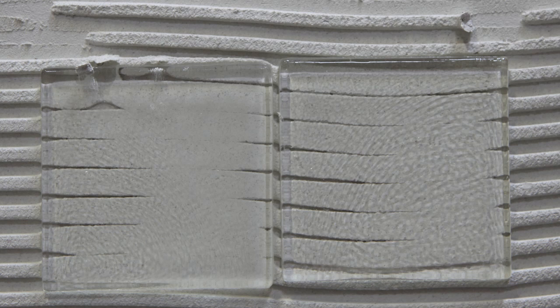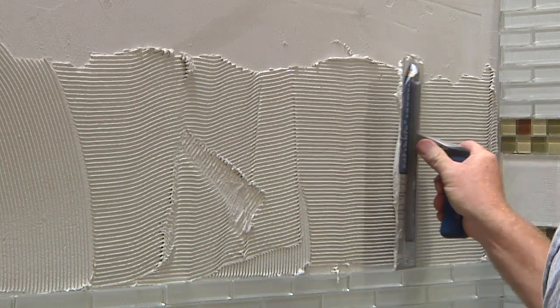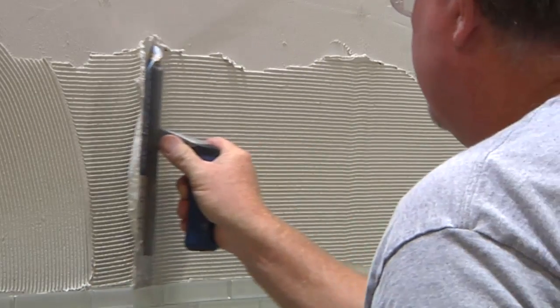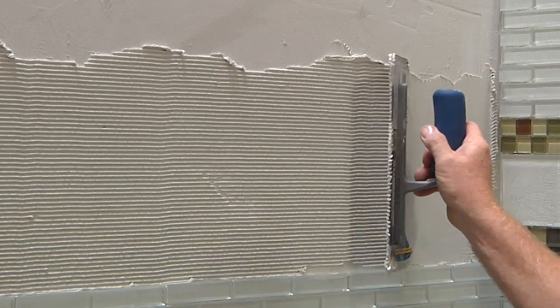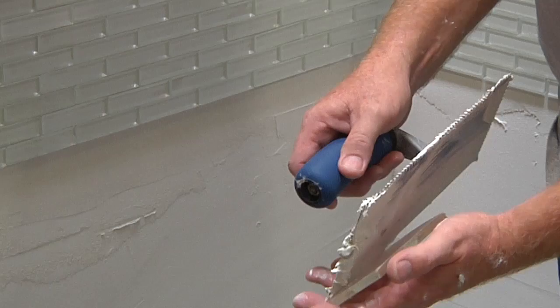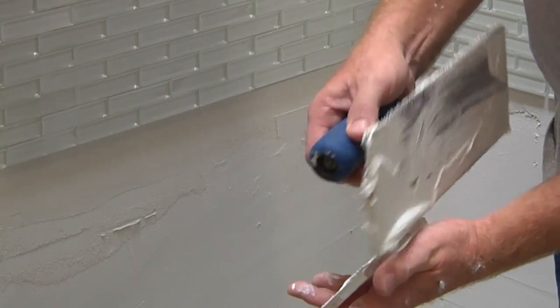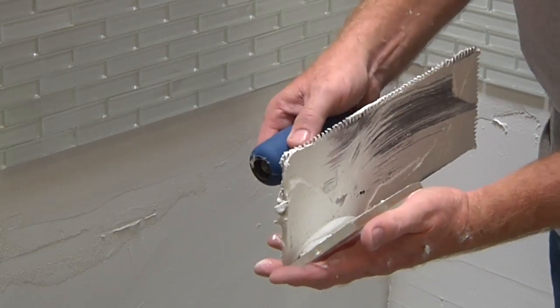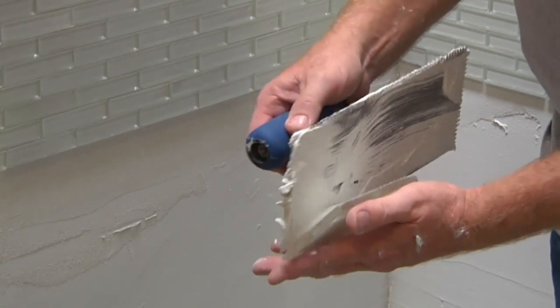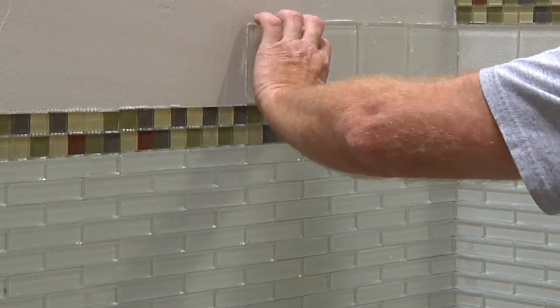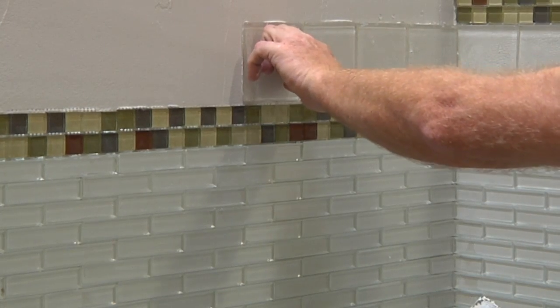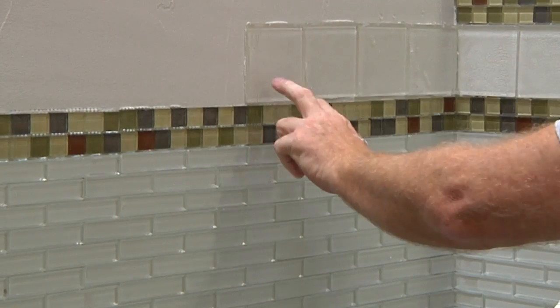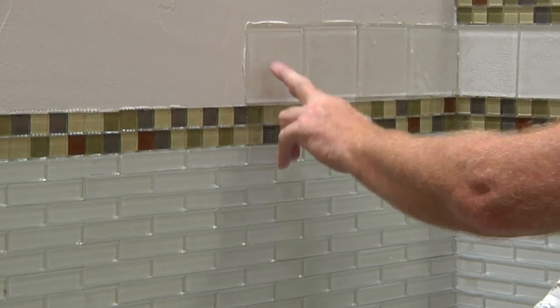To avoid air spaces behind the tile, the proper installation method is to trowel the specifically formulated glass tile thin-set mortar on the substrate with a notch trowel, but this time knock down the ridges. Then spread or back butter an even thin film about 1/16 of an inch thick onto the back of the clear glass tile. These two mortared surfaces are pressed together with a back and forth motion to eliminate any voids.